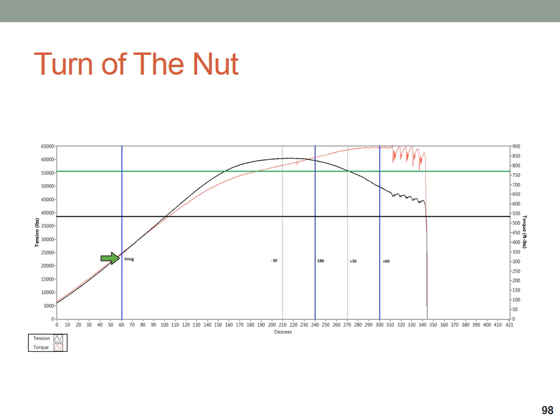Even me with a spud wrench can probably turn a nut about 60 degrees and develop a pretty high level of snug tension. In this case, that would be 20 or 25,000 pounds of tension on a 7/8 diameter bolt, for example. That becomes the point where we measure 0 and, in this particular case, add 180 degrees of turn. And this is where I find it interesting that we have the ability now to really see what's happening to capture this data as we install bolts, nuts, and washers and capture the degrees and the tension and the torque.